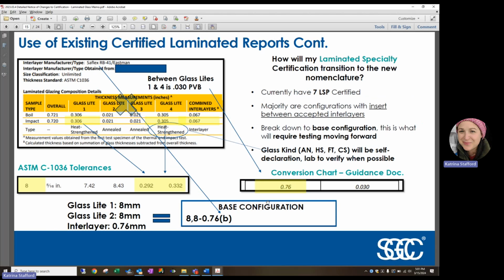This is an example of a current laminated specialty product that we use to break down this configuration. Many of our laminated specialty products now contain inserts that are encapsulated between two approved interlayers and therefore are covered under the base construction and do not need to be tested and certified separately with this new laminated guideline change. SGCC's main focus is to test the adhesion of the interlayer to glass. So anything that's encapsulated between two already approved interlayers is covered by the base construction.